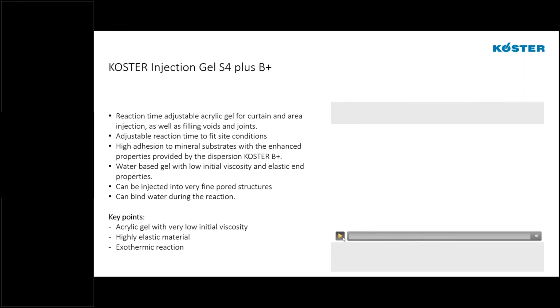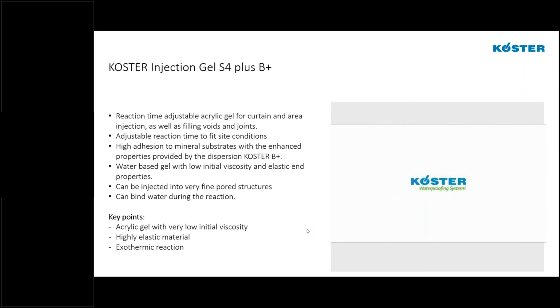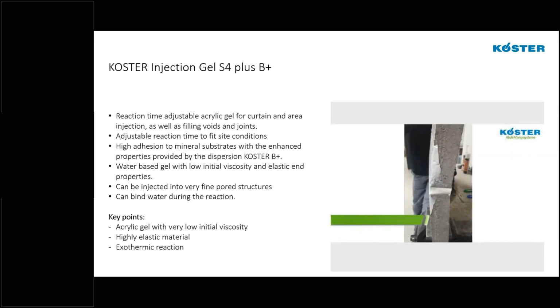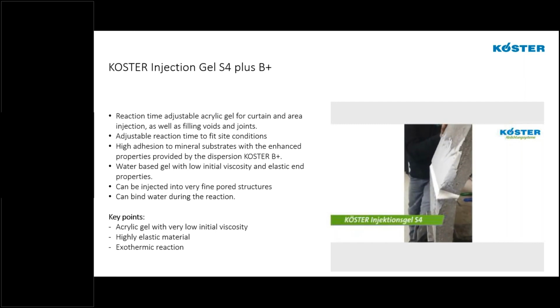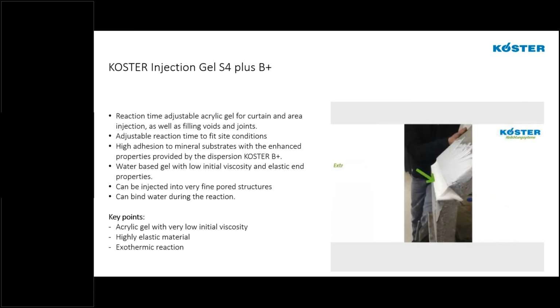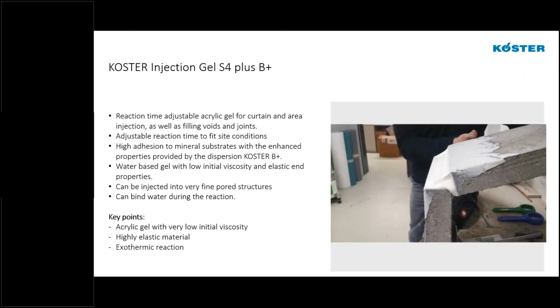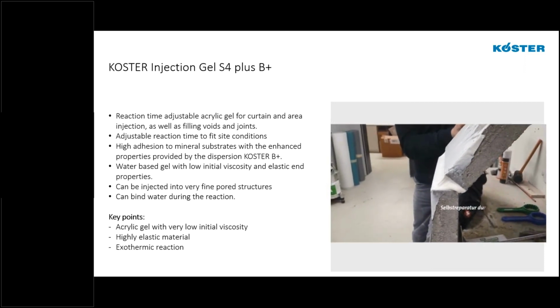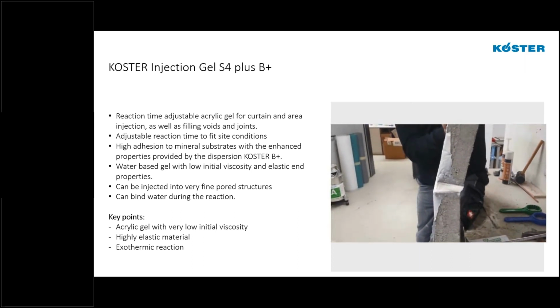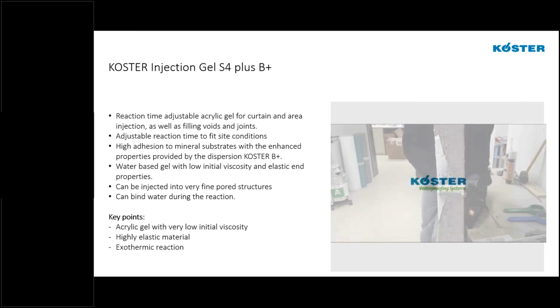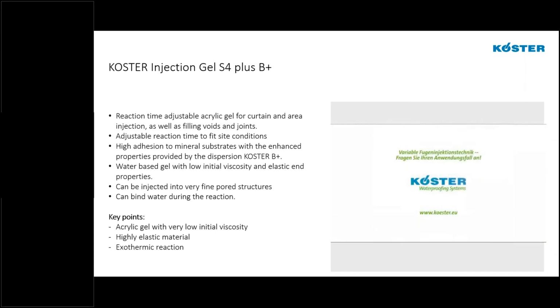It just shows the flexibility and the actual elasticity of the material. So this is a joint that's been sealed with just gravity fed in with the S4. So filling a joint of here 1.5 centimeters, and it has obviously extremely high bond strength to the flanks of the joint and over 500% elongation. So we can see the great stress that we can put this under, and we have no kind of distress or failure of the system at all. So it is a very, very elastic joint sealant, which we can use for any kind of shear exposure, as well as the normal expansion and contraction of a construction joint.